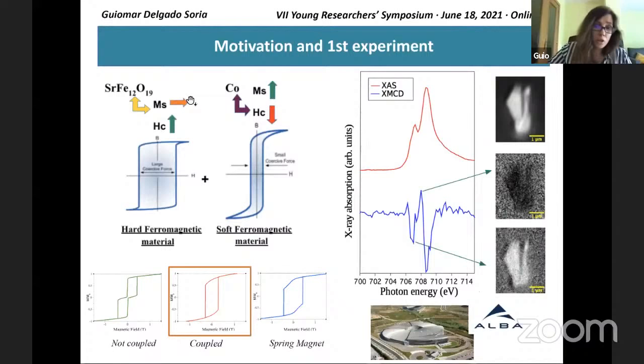But there is an issue: the saturation magnetization is relatively moderate. It is well known in the literature that when you combine it with a soft material, a metal layer, in our case cobalt, you can improve the magnetization without a significant coercivity cost. But for this combination of layers, we need a magnetic coupling between them. For this, we did different experiments.